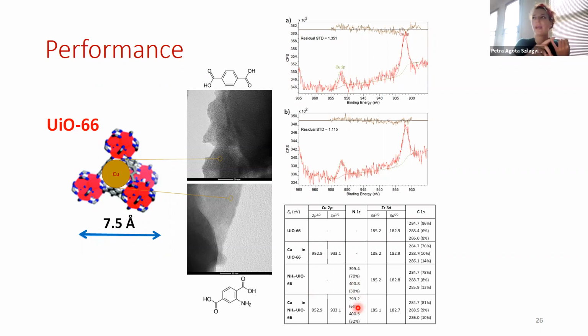So what you could see from there is that there is confinement effect, and there is no strong host-guest interaction, so we can exclude any kind of electronic promotion effect in this case. And more importantly, because the catalyst particle size is the same, the surface chemistry is the same, so any difference in the performance of these two materials or matrices could come down to the presence of the amino groups in the framework. And what we found was the following.